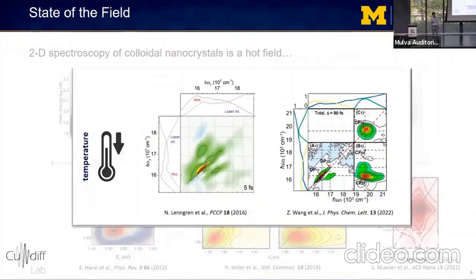If you lower the temperature, however, intricate line shapes appear that give you access to a whole new range of physics. So for example, there was this beautiful work that came out of the groups of Tonu Pullerits and Gediminas Juzeliūnas, where they observed narrow exciton line shapes at liquid nitrogen temperatures. So this was our motivation to try 2D spectroscopy of colloidal nanocrystals at even lower liquid helium temperatures to really try to measure the intrinsic properties of excitons of these nanocrystals.